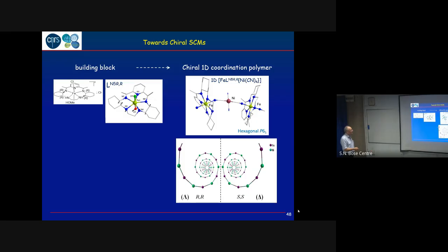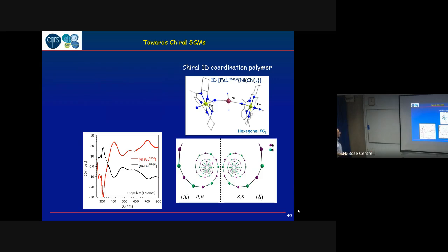And what you can see is, if we start with the R enantiomer, so with this one, we get a helical chain that is left-hand turning, and if we do the chemistry with the related S, we get the same chain, but now the helix turn is right turning. So here we control the stereochemistry at the metal center, but also at the supramolecular level. These are the optical properties, the CD spectra of the two species, just to show that indeed we really play with two enantiomers.